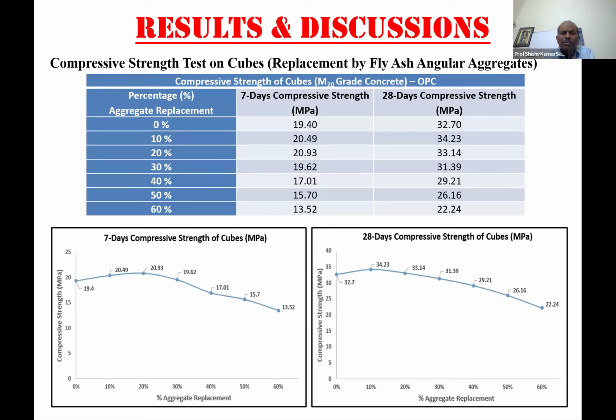Cubes replacement by fly ash angular aggregates. Have I told you how to manufacture fly ash angular aggregates? Actually, we have done it like this. Fly ash angular aggregates we have manufactured in two ways. One, we have added fly ash with an admixture, which is gum-like. Then put it into the furnace. Something like 1250 degrees gives us the aggregate.